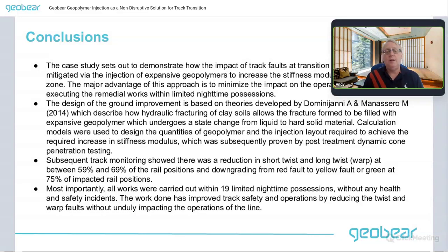So, in conclusion, this case study sets out to demonstrate how the impact of track faults at transition zones can be mitigated via the injection of expansive geopolymers to increase the stiffness modulus of the soils within the zone. The major advantage of this approach is to minimize the impact on the operation of the railway by executing the remedial works within limited nighttime possessions.